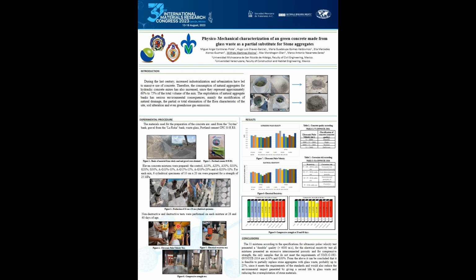The non-destructive tests performed were ultrasonic pulse velocity and electrical resistivity, both performed at 28 and 60 days. The only destructive test performed on the specimens was the compressive strength test at 28 and 60 days.